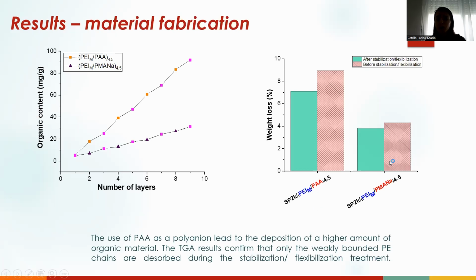The stability of the composite materials to rinsing and stabilization flexibilization treatment was assessed using thermogravimetric analysis before and after the stabilization flexibilization. We observed that, comparing the weight loss for the composite materials before and after stabilization, the difference in the amount of organic material thermally degrading was less than 20%, which confirms that only the weakly bound polyelectrolyte chains were extracted during the stabilization flexibilization treatment.